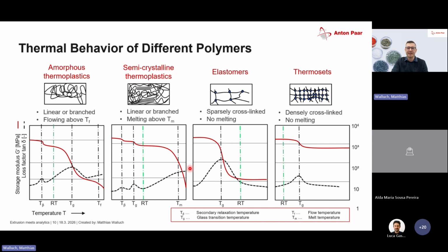For elastomers, it's again a little bit different. We have room temperature in green, and the glass transition is far below room temperature. So in this area, for example at minus 100 degrees, the material would be very stiff and very rigid. Once we are over this glass transition, the material gets much softer. And here we have the area where we use these materials and where we can benefit from the specific material properties that are due to this low, sparsely cross-linked system.